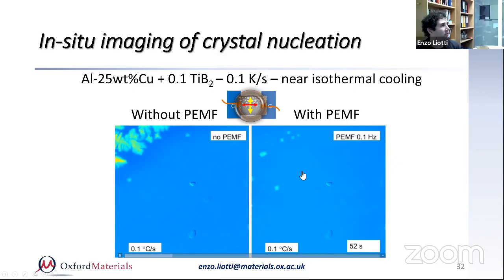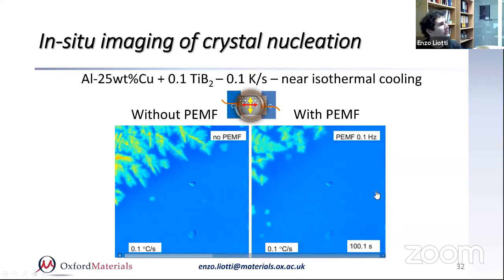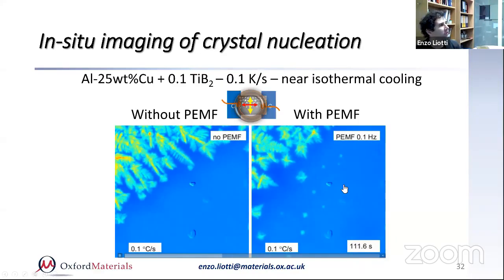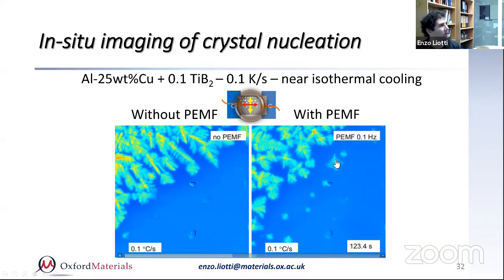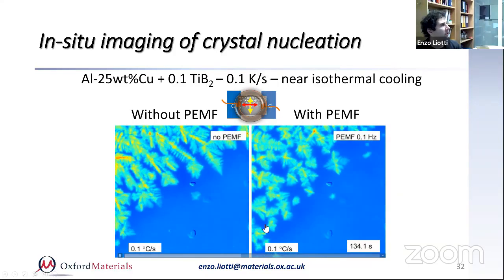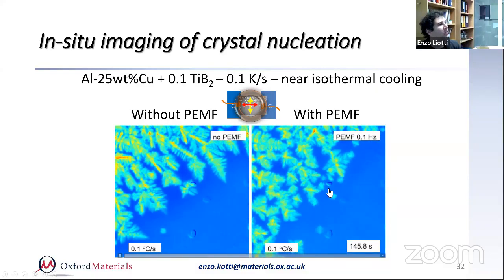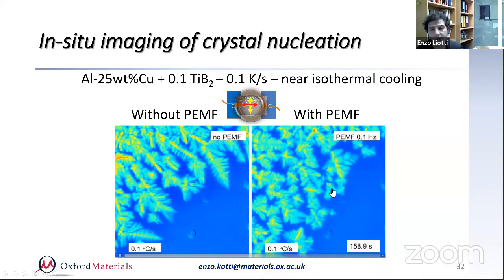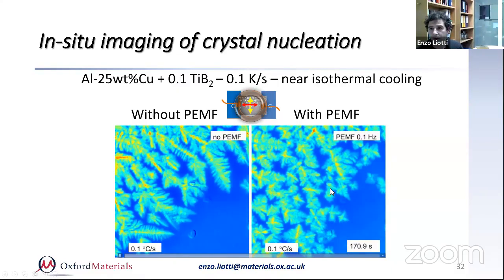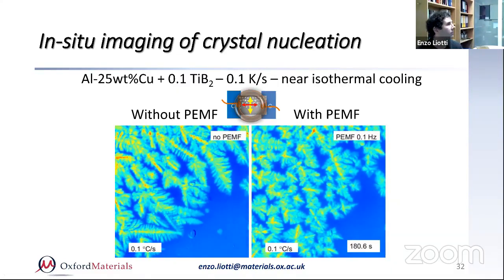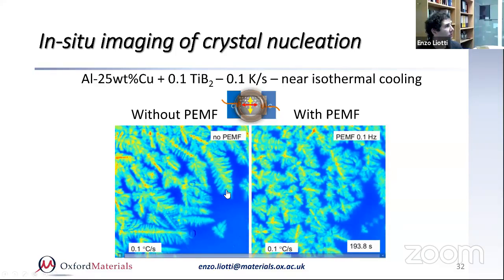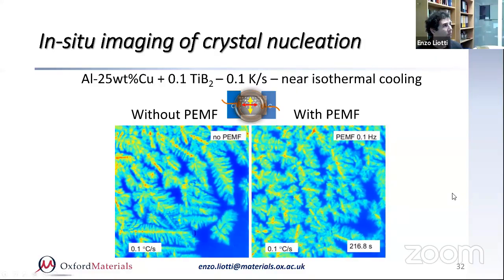And we can see that the dendrites are shaking and are appearing in the field of view and going. But apart from the nice fluctuation of the dendrites, one evident case is that this stirring is increasing the nucleation rate. If you look carefully, even without counting, you can see there are more grains forming here than here. And the second effect: they impinge on the growing dendrites, effectively blocking the growth of the columnar grain. You can call it a sort of induced CET, right? And if you look on the left, in fact, there is not much nucleation and the dendrites are happily growing, basically a columnar structure. So that's an example.